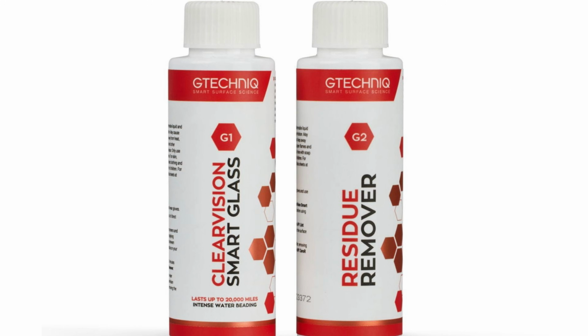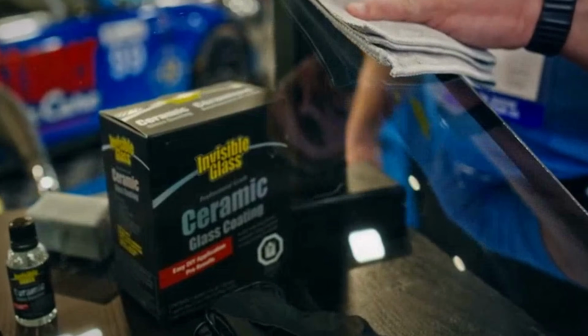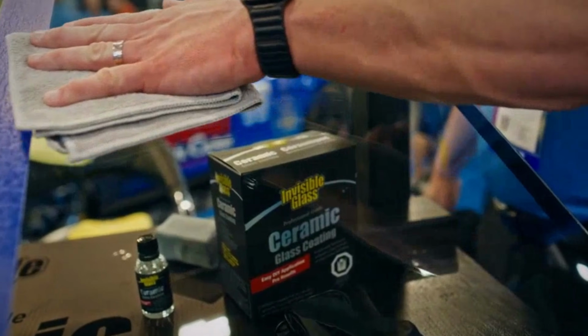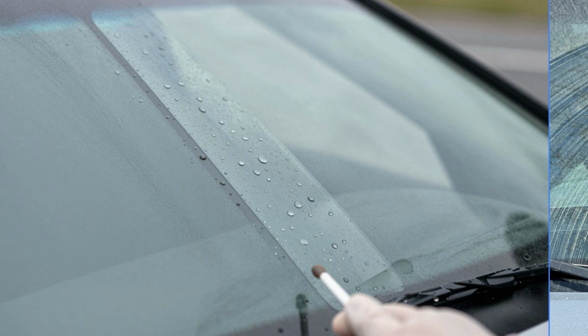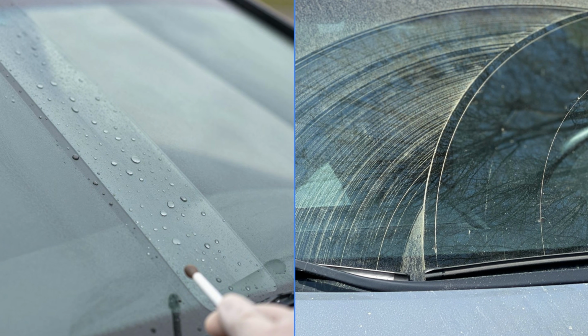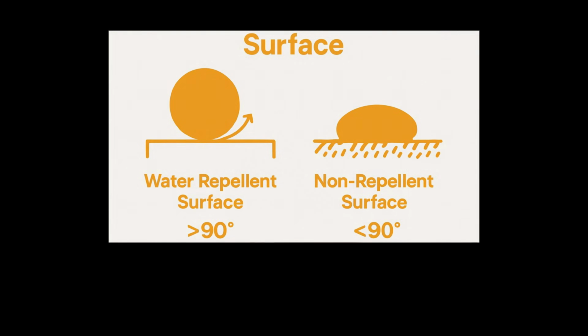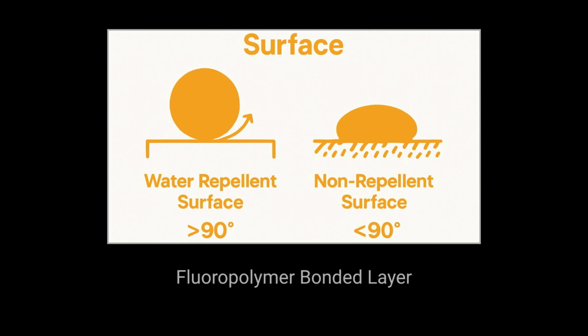Then use the residue remover included in the kit to wipe off the uncured excess. This is critical. If you leave uncured residue on the glass, it will cause wiper judder and smearing for weeks. Wipe it off methodically with a clean microfiber towel. The glass underneath should look completely clear, because it is. The coating is invisible. It is not a film. It is not a layer. It has chemically become part of the glass surface.